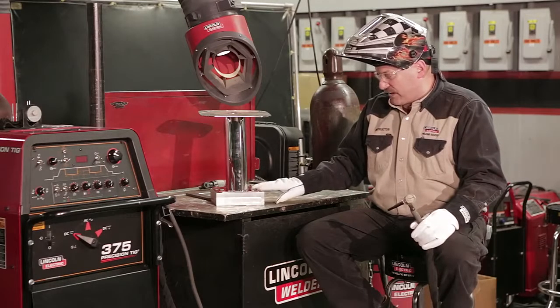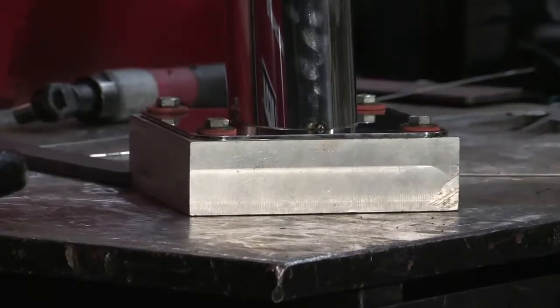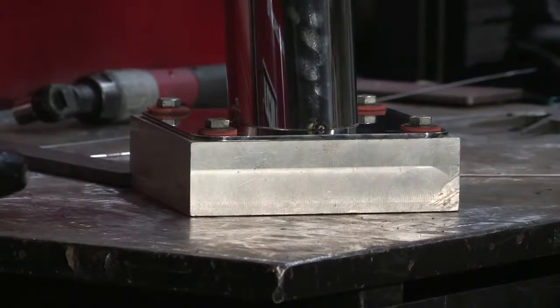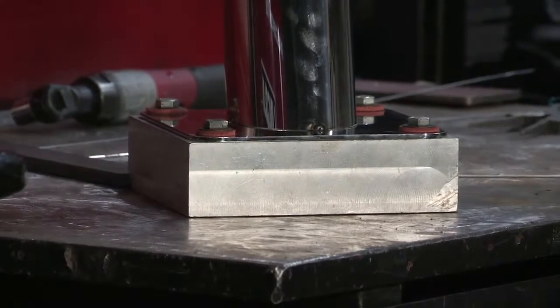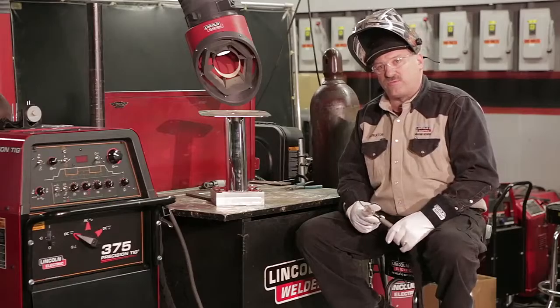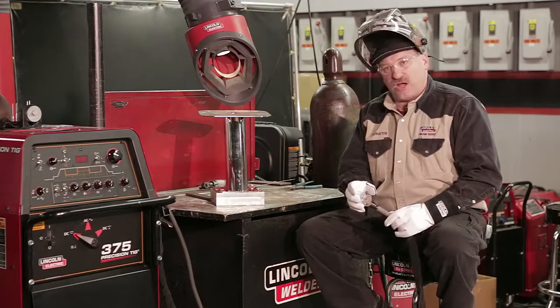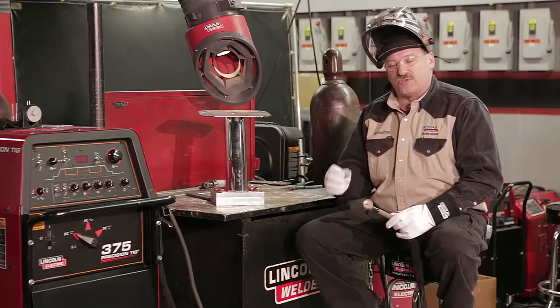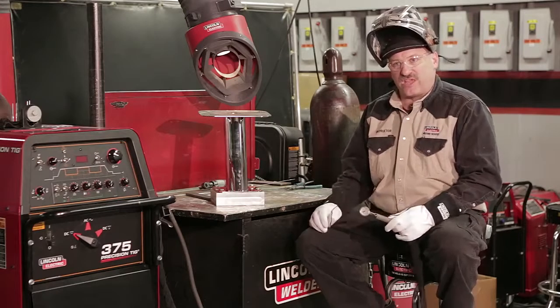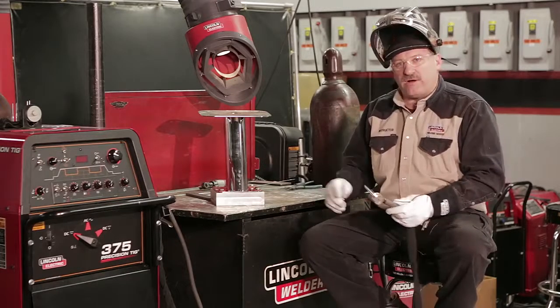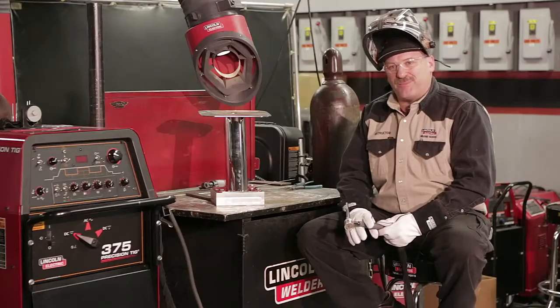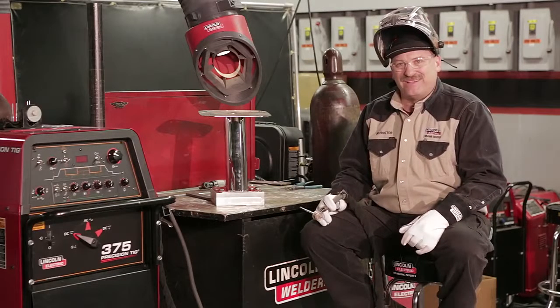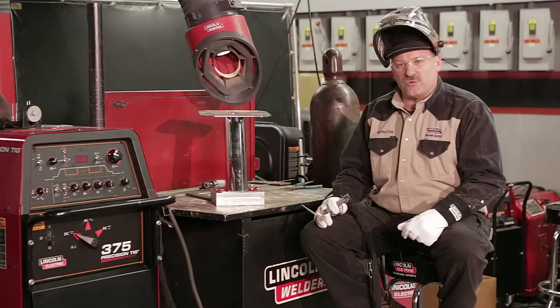So I bolted this down onto this heavy block as a heat sink and also to keep the stainless from distorting. I'm going to try and keep my heat input down by keeping a close arc length with my tungsten, using a large cup to keep the shielding on as long as possible so I don't get that blue color. I want to keep the stainless shiny. These will get buffed after I'm done welding them, but it makes the buffer's job a lot easier if I keep my shielding on until the piece cools down.